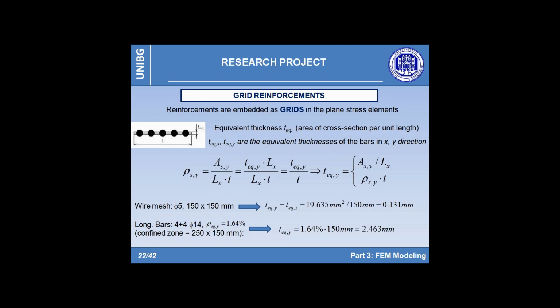0.131 millimeters. In the same way, knowing the percentage of longitudinal reinforcement, it's enough to multiply the latter by the host element thickness. For example, being 1.64% the reinforcement percentage of the confinement zone, the Y equivalent thickness results equal to 2.463 millimeters. So, following this example, the X and Y equivalent thickness have been calculated for all the previous areas.